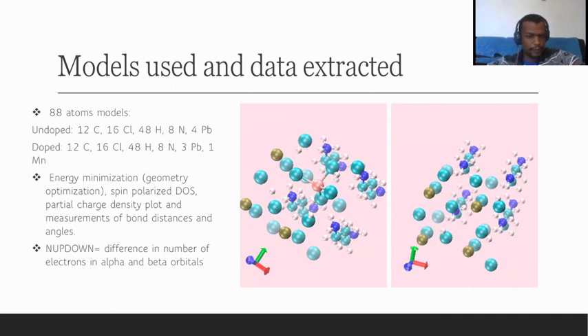DFT calculations using VASP software were used to extract the lowest energy configuration during the geometry optimization, and compute the spin polarized density of states, partial charge density orbitals, and I also measured the bond distances and angles. I also want to note that N up down is defined as the difference in total number of alpha electrons minus beta electrons. It's going to be relevant in future slides. The next slide, please.